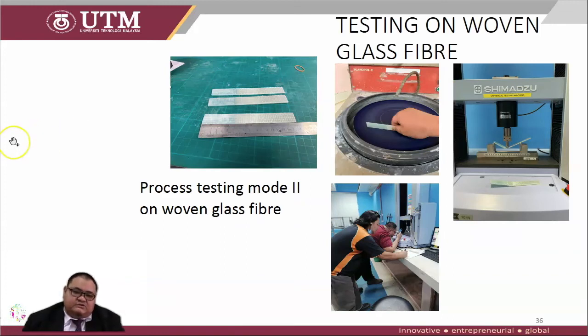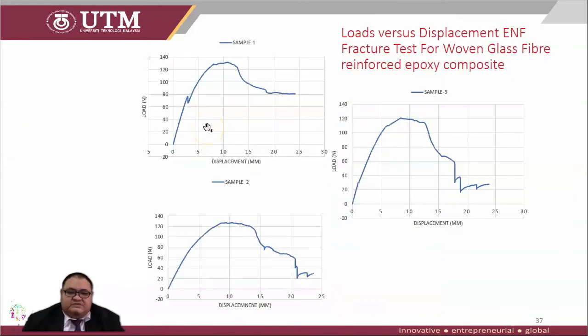This is the Mode II process on woven glass fiber. This is the testing machine and specimen. This is the load displacement in the fracture test of woven glass fiber reinforced epoxy composite. This is the result of the testing. We can see sample 1, sample 2, and sample 3 have the same pattern on the graph, where P maximum is around 120 Newton to 140 Newton.